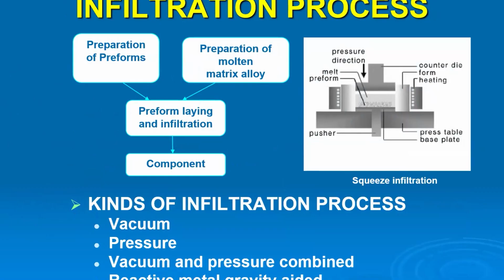The next process is called the infiltration process. Here we make a porous preform of SiC particles or any particles, we preheat the preform, place it in a die in a press, then we pour the metal and apply the ram. Then the metal gets infiltrated, and we can have vacuum infiltration, pressure infiltration, vacuum and pressure, or reactive sintering.